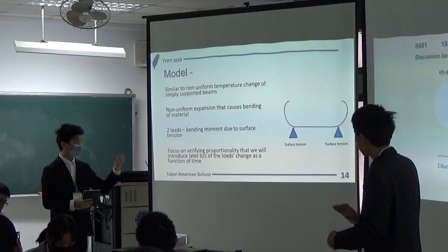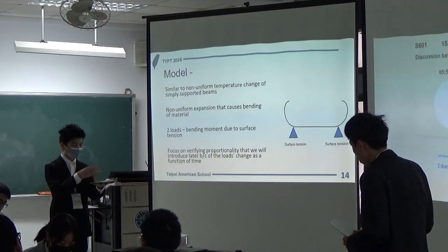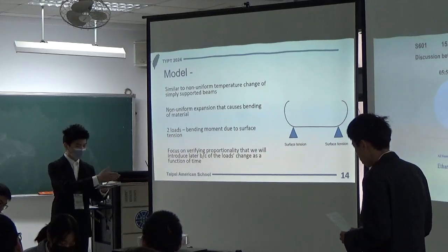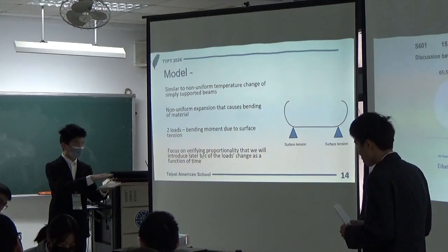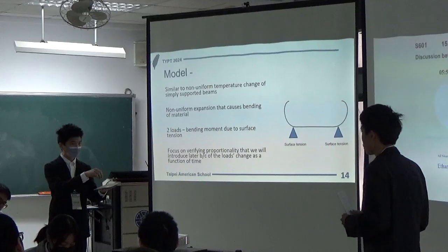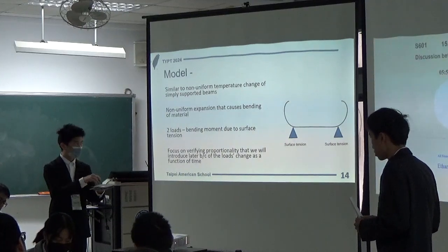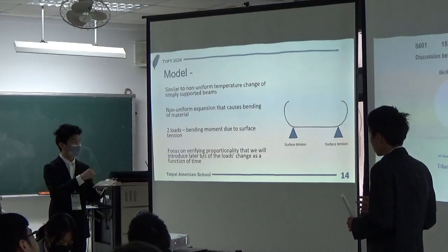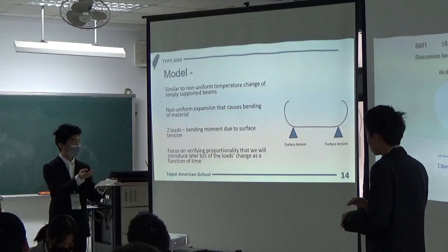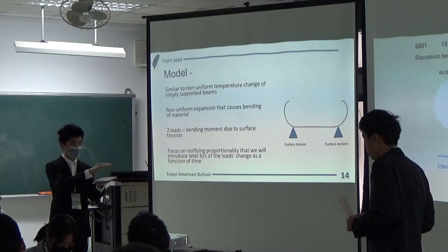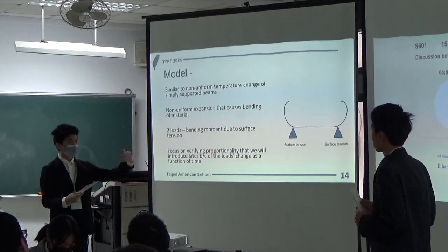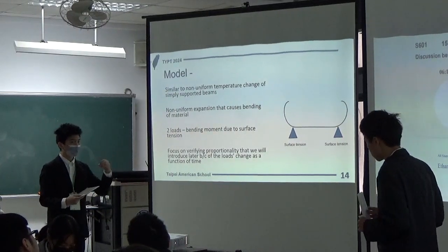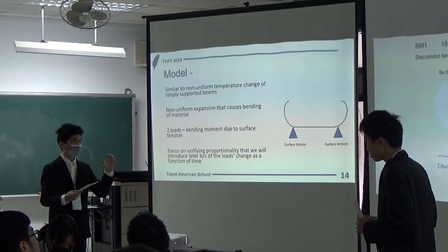So basically the reason why the paper curls up slowly and has a section that stays flat is because of both gravity and surface tension. Yes. However, surface tension is much greater than gravity. So the surface tension is primarily what causes most of it to stay flat as it curls up. However, if we were to reduce surface tension by a lot, then it would curl up at a much faster rate. So there wouldn't be that big of a flat area, and the limit between double scroll and single scroll would almost always be single scroll.